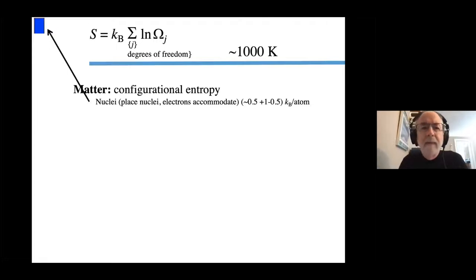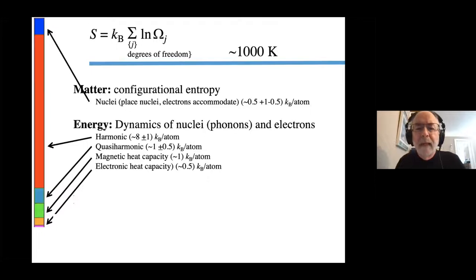Now, at 1,000 Kelvin, you have a lot of excitations of degrees of freedom. The amount that can be explained by a harmonic model is on the order of 8 Boltzmann's constant per atom. So these are vibrations of nuclei primarily. That's where the mass is. We have to correct that for thermal expansion, and that's a quasi-harmonic correction, which is about as big as the configurational entropy is. If we have a magnetic metal, we have the spins, which we can disorder and get additional entropy, and the electrons can get excited above the Fermi level. So these are all textbook topics that you can look up in Ashcroft and Mermin if you like.